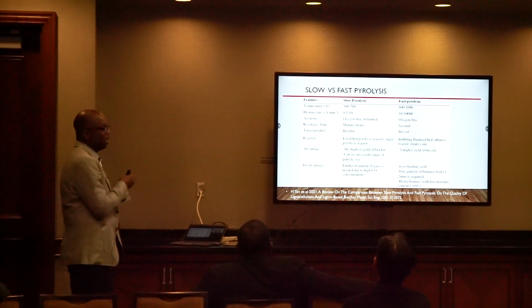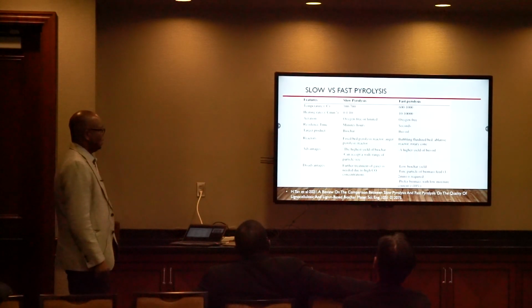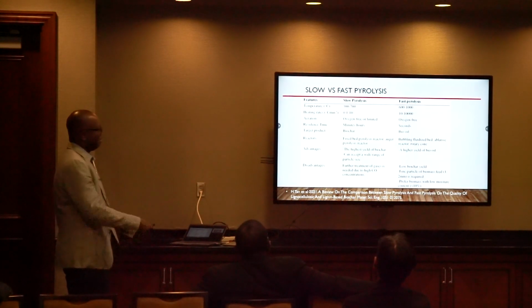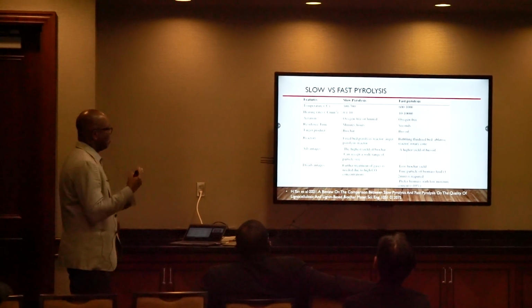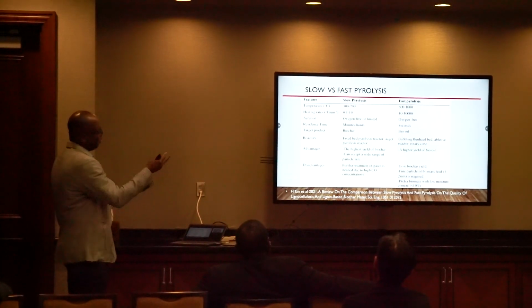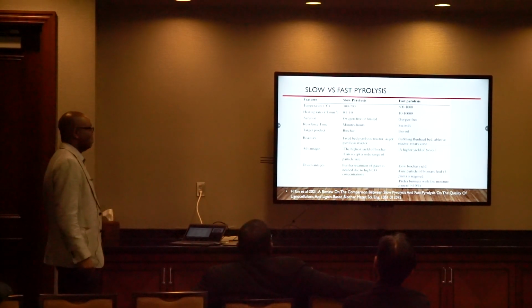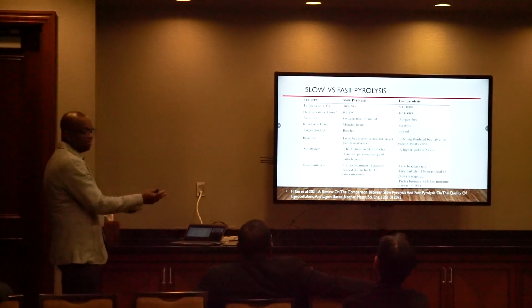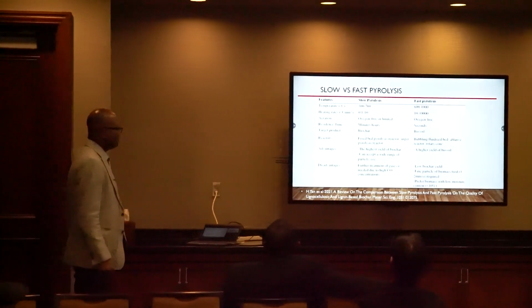So if you are interested in making biochar, then you have to make sure that your heating rate, all the parameters that go with slow pyrolysis, especially the heating rate and the heating temperature, you pay attention to those. And then, of course, if you are interested in the bio oil, then you can go for the fast pyrolysis. There are advantages and disadvantages for both the slow and the fast pyrolysis.